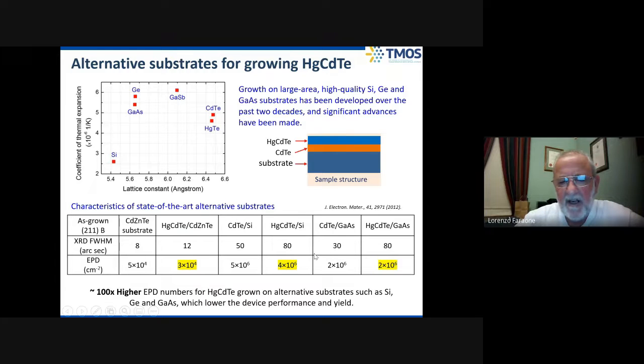I won't go into detail here, but if you try to grow mercury cadmium telluride on silicon or on gallium arsenide, you end up with etch pit densities in the low to mid 10 to the 6 per centimeter squared. Whereas if you grow on the lattice matched cadmium zinc telluride, you're about 2 orders of magnitude lower than that. So at this stage, there's still no alternative, certainly for high performance imaging arrays, except to grow on cadmium zinc telluride.